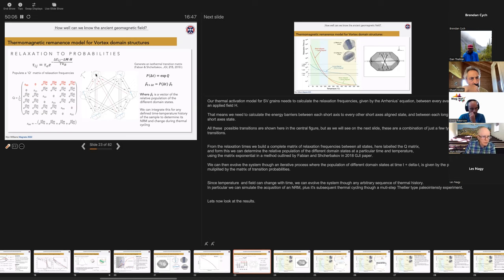This is unlike multi-domain grains, though, because the domain states have high remanences. The number of domain states are fewer and behave in a more predictable way. The very large PTRM failure and PTRM tails in our example are the result of large differences in the remanences of the different allowed domain states. And the fact that the energy barriers between the different domain states change at different rates as a function of temperature. The extreme reciprocity failure shown in our example are seen in single vortex grains that have multiplicity of different domain states, which may be predictable. And you might argue that that actually the number of grains that have this multiplicity of domain states is actually very narrow and larger grains are going to be slightly better behaved, maybe predominantly vortices aligned with the easy axis.